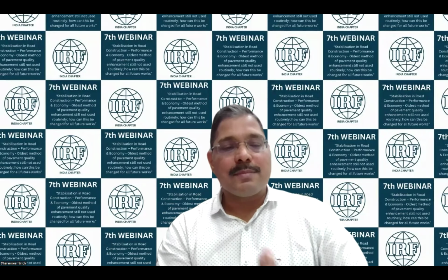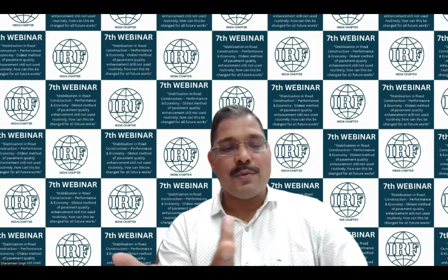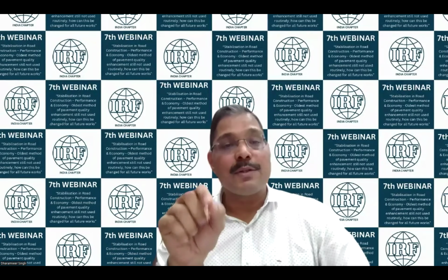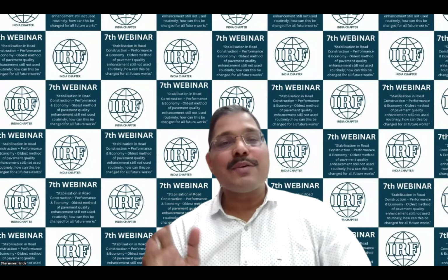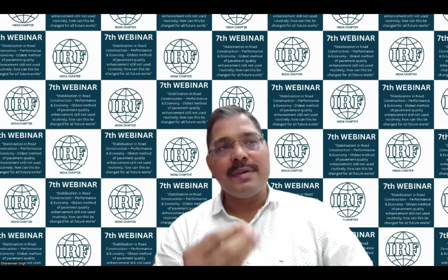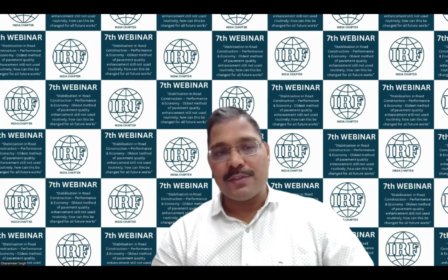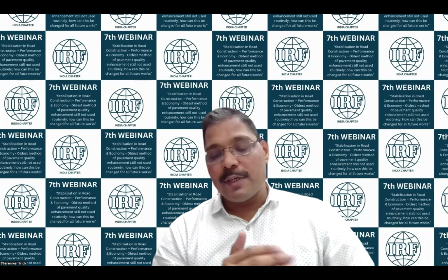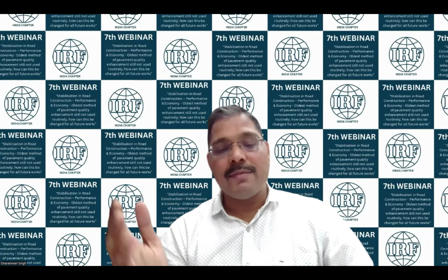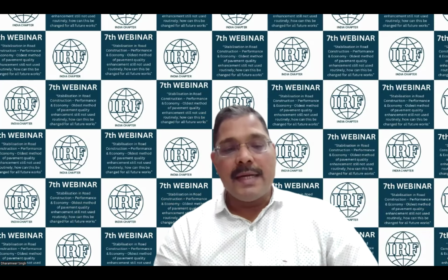Anyhow, naturally your VG40 will also give you close to 52 or 53. And there are fines also in the RAP, because you cannot exclude all the fines. So softening point will naturally increase up to 58 or so. So unless you are getting a softening point as high as maybe 80 or 85, or maybe more than 75, it's not a stiffer RAP.